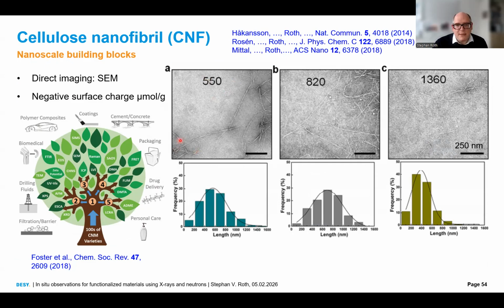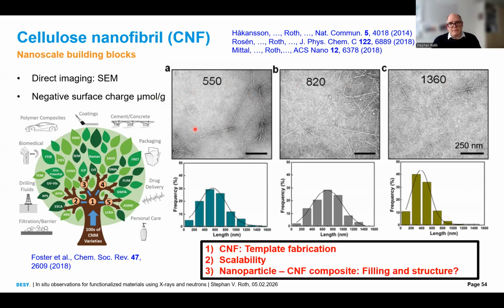chemical methods, we can introduce a surface charge on them. And the surface charge is in micromole per gram because they are carboxylic groups. And the higher this number, the higher the surface charge. So the surface charge here is given as micromole per gram. So we take these cellulose nanofibrils, we disperse them in water.